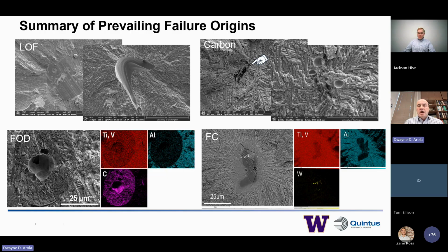And then also we saw some foreign contamination. We don't call this a FOD yet because you see a region that's aluminum deficient followed by a region that's aluminum rich, and you don't see a discrete particle boundary. You see, for example, an integration of that particular material with the surrounding titanium 6Al4V matrix.